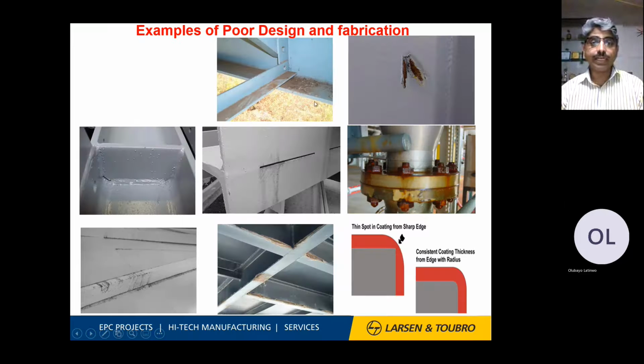Coming to certain poor design examples, this is what the structures are. Normally bolted structures always have certain gaps, and these gaps are prone to corrosion. There are certain cases where there are lamination defects in the plate material, which get peeled off after painting or sometimes during service for certain structures. Certain spatters are there, which is a welding error. They are not removing them, and they don't dress up the joint properly, so this is prone to early corrosion.